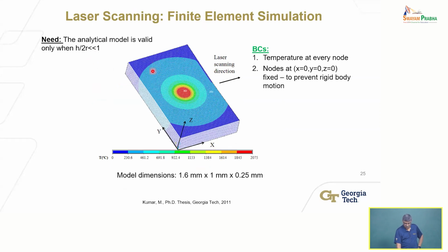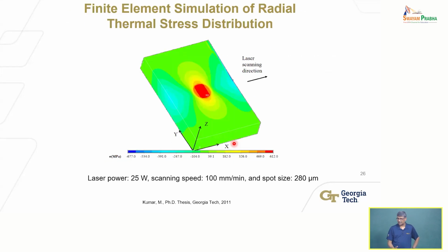So we use a finite element simulation where I can relax many of these assumptions, and apply the boundary conditions. I'm interested in room temperature at every node, so you start out with some temperature, in this case whatever temperature distribution is imposed by the laser on top of it. And then you fix all the other nodes at the bottom, so you don't have rigid body motion. Otherwise you won't be able to solve the problem, right? And you solve this, it gives you the temperature distribution. From the temperature distribution in a finite element model, you can also calculate the stress distribution, right?